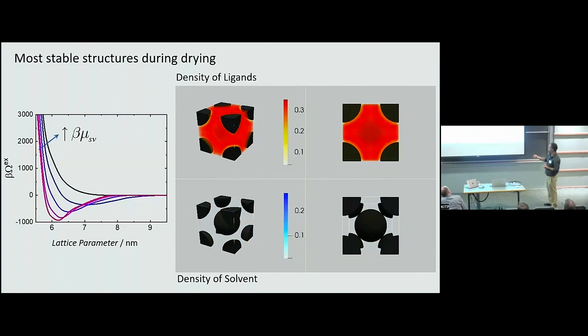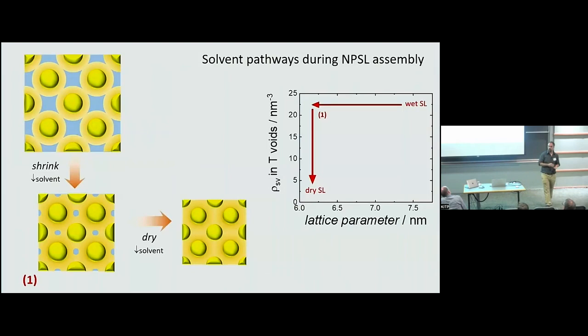All right, so what can we do with this? Well, we decided to first check the approximation that we used in the other theory, this incompressibility constraint. That approximation will basically tell you that if you start with a superlattice that is swollen with solvent, and you want to go to a dry superlattice, then the first step will be to shrink the lattice. That, of course, will expel solvent from the system. But if you look at, let's say, the density of the solvent in the voids, that should be more or less constant because of this incompressibility constraint. You don't have ligands here. So the only thing that you're going to have is solvent, right?